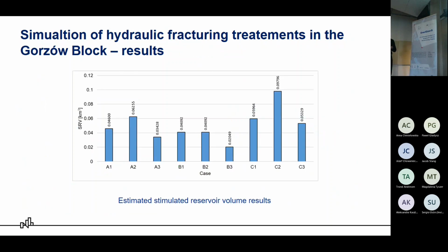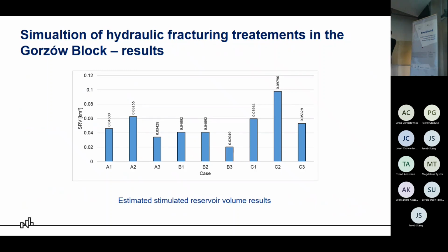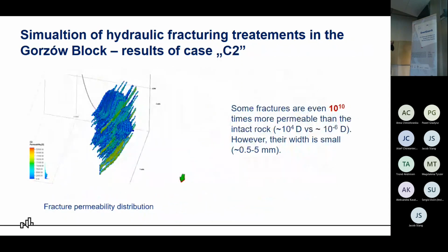principal stress. And comparing different scenarios, we see that the stimulated reservoir volume was the highest in the C2 case. It's about 0.1 cubic kilometer. So this volume, 0.1 cubic kilometers, is the enhanced permeability zone, and this should be enough to drill another well which crosses this section. Let's say this injection well, then a production well should be drilled to cross this zone of enhanced permeability, and then it should be enough to sustain the fluid flow.